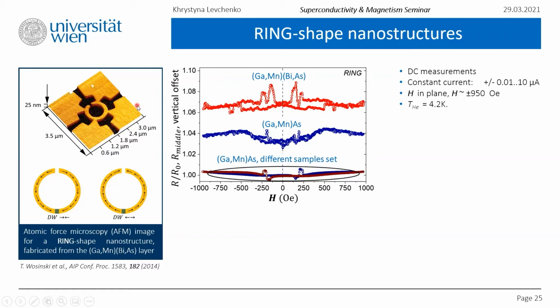For now, let us concentrate on the materials at our hands. So we described the crystalline strain-induced magnetic anisotropy, that it leads to either in-plane or perpendicular magnetization. But it is also possible to introduce a pattern-induced anisotropy by smart lithography. Smart nanostructurization of the layers that are grown under compressive strain will create an additional degree of freedom that can be used in device operation.